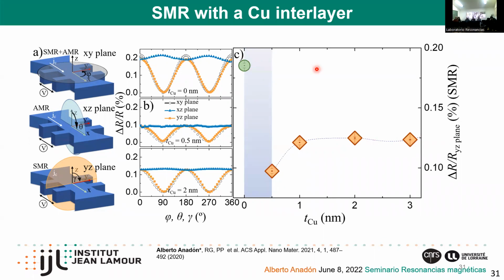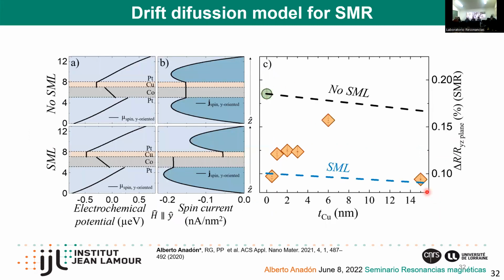So basically, the spin memory loss is reducing the spin current in the system significantly, but this cannot explain everything that we are seeing. So basically, if we go further to even up to 15 nanometers of copper, and we put everything in a diffusion model to understand how is the spin accumulation and spin current in the system.